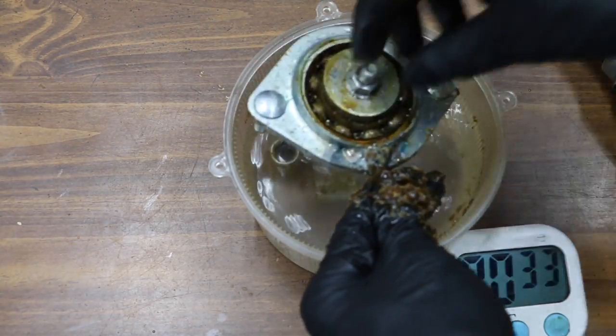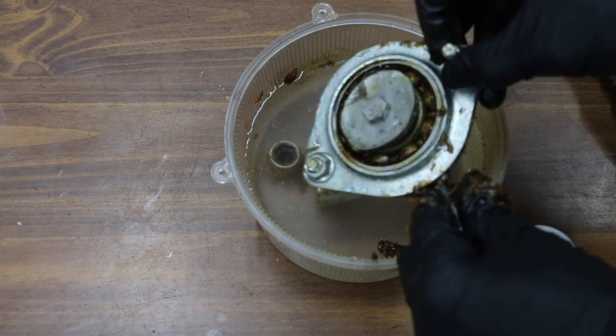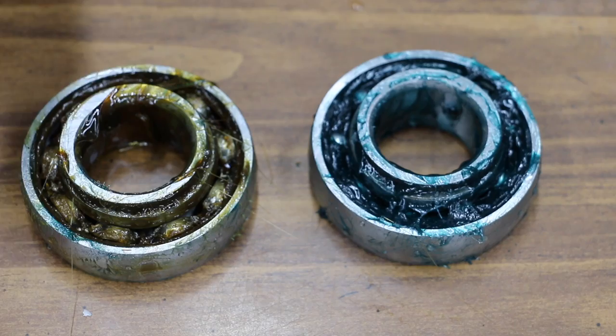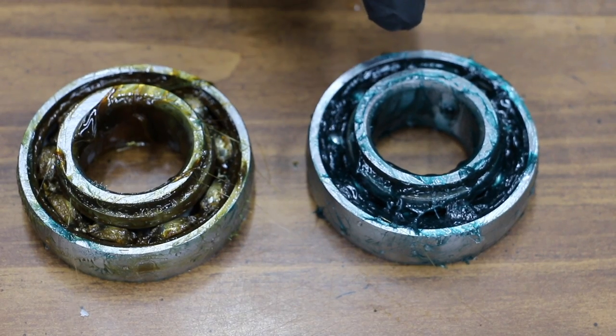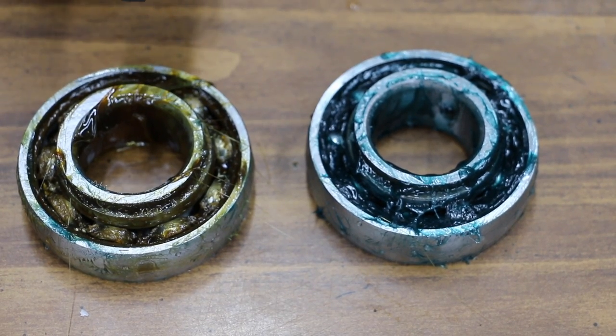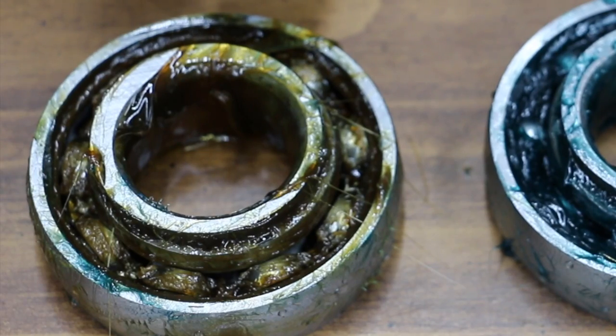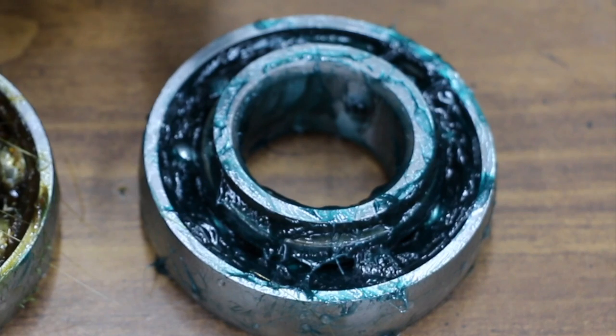Wow, there's not much grease left in these bearings. The water really washed away the grease. The vintage grease is on the left and the Mag 1 is on the right. There's a huge amount of difference between the two. Just like we saw with the water spray-off test, the vintage grease just washed away when exposed to water. There was definitely some wash away with the Mag 1, but it did a very good job.